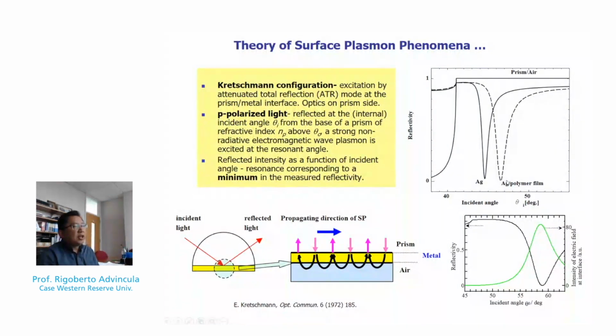And in fact, this shift, if one can model it using different algorithms based on Fresnel algorithms, one can actually calculate the thickness and/or the dielectric medium. The other aspect is that this type of experiment is very sensitive to polarization, such that an S or a P mode can be distinguished based on the type of polarization experiment one does.